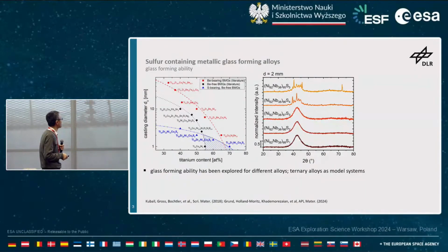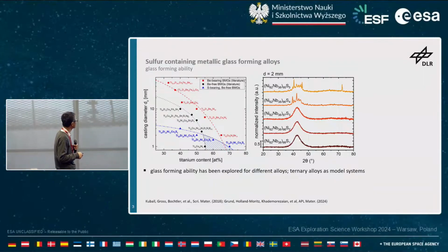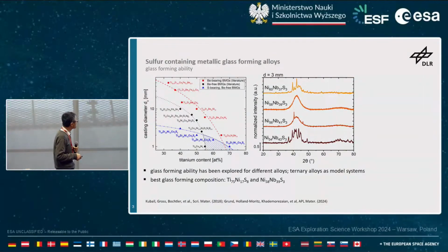This is just to show you how the alloy development has been done. So basically the glass forming ability, or how good or how easily they can form a glass and avoid crystallization. What we are especially interested in is that when you have a melt and quench it, it does not crystallize, depending on composition. And this is just to show you how this has been mapped. If you start from simple alloys, so ternary systems, in our case this is usually low, and how this can be developed into more complicated systems. But for carrying out physics studies, we are especially interested in these ternary alloys as a model system, because they are easier to understand.